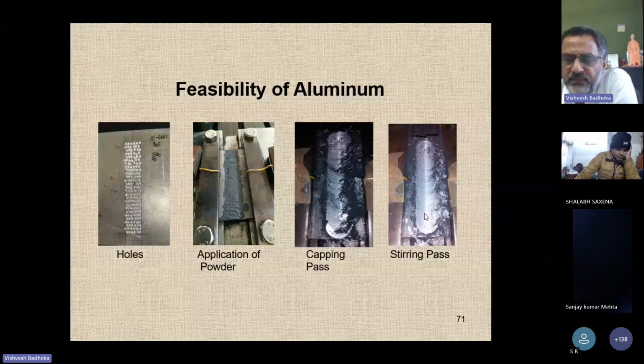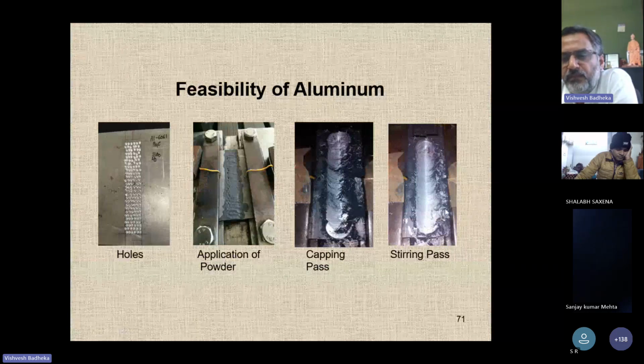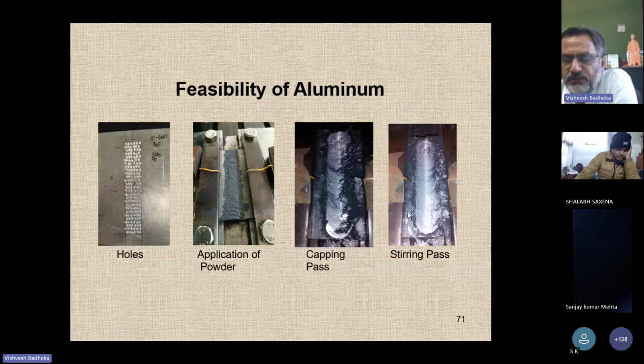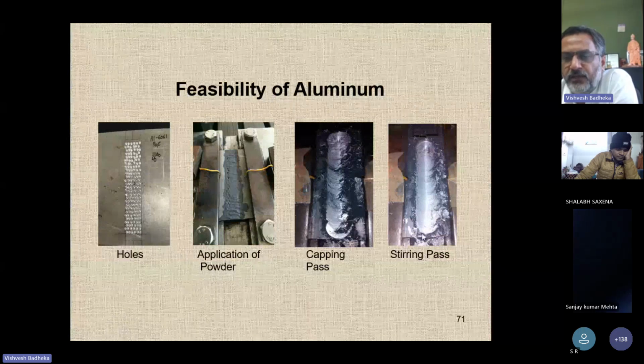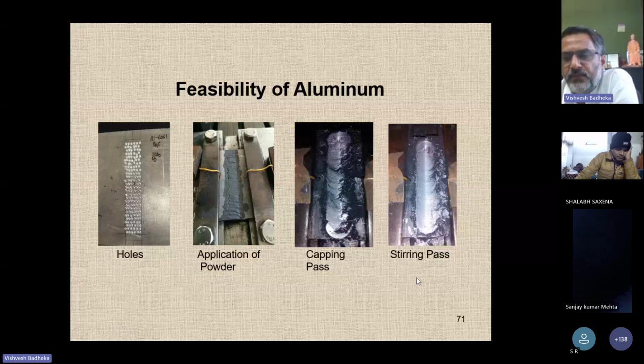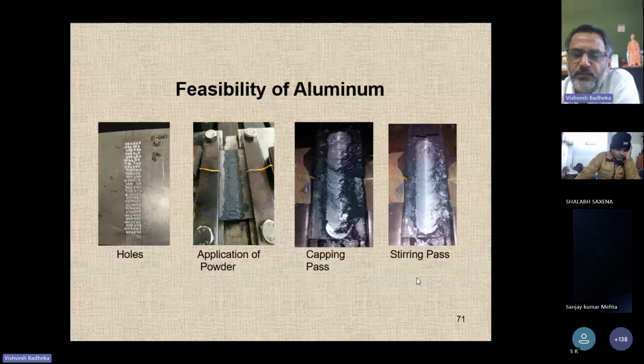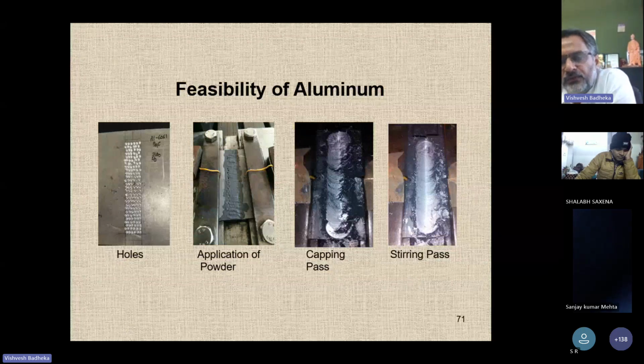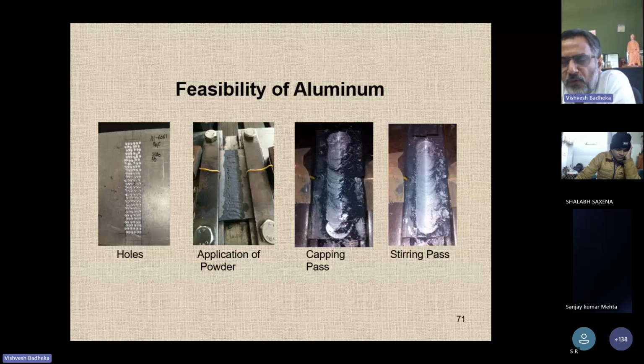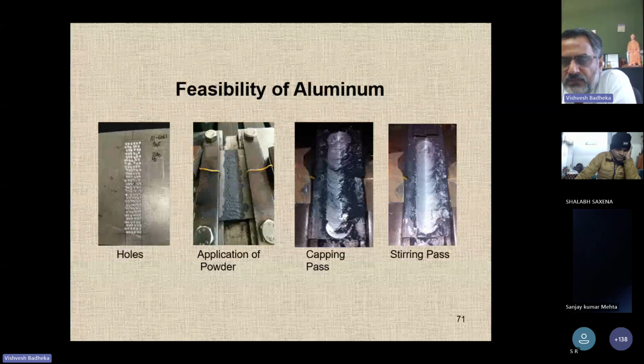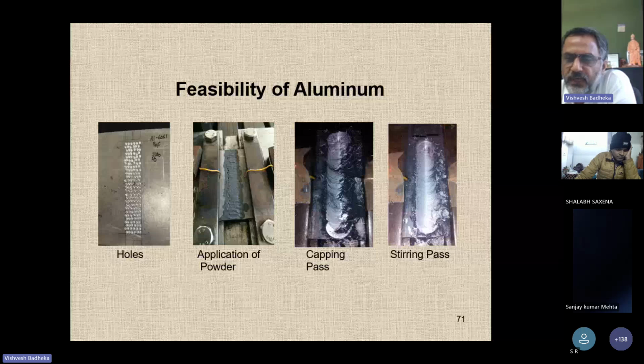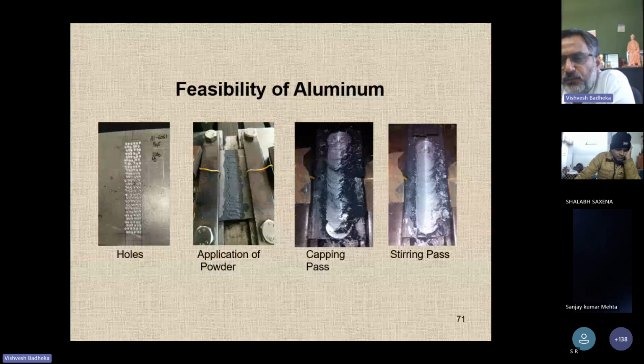Now, after applying the stirring pass 1 time, the same area can be processed with additional stirring passes also. Say, for example, you have done one stirring, now in the same area you apply a second stirring, a third stirring. With additional stirring passes, you are trying to ensure that the powder mixes more uniformly into the matrix, so that there is no agglomeration of the particles, and there is uniform distribution of the reinforcement particles in the aluminum matrix.